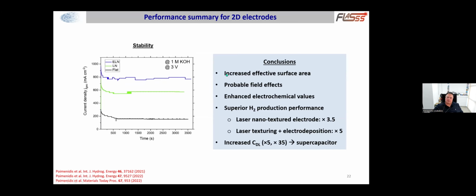So concluding, I would like to say that we observed increased effective surface area after laser irradiation of metallic electrodes. However, along with the increase in the effective surface area, we expect also the field enhancement at the nanoparticles that are scattered on the surface to have their own contribution in the increased performance of these electrodes. This is yet to be examined in our research. Moving on, we observed and measured enhanced electrochemical values, and we observed a superior hydrogen production performance, which reached the value of 5 times when compared to the traditional electrodes. And we also measured very much increased double layer capacitance, which is important when one thinks of developing supercapacitors.